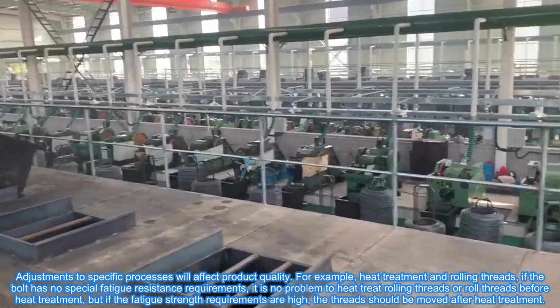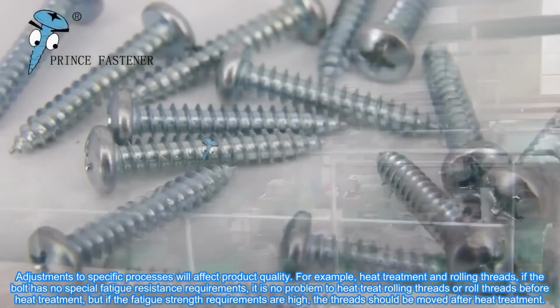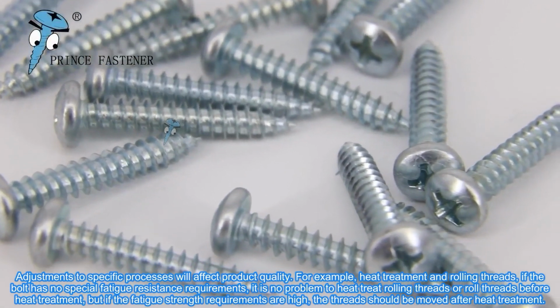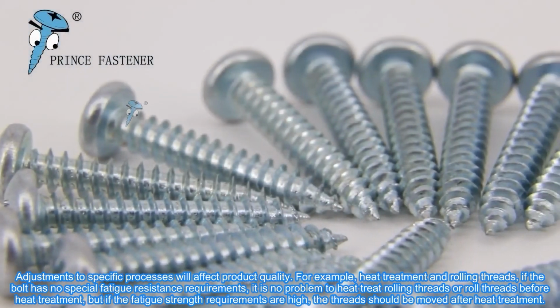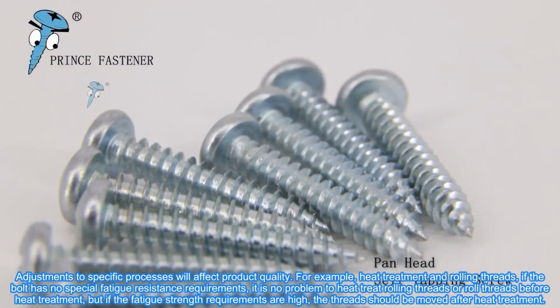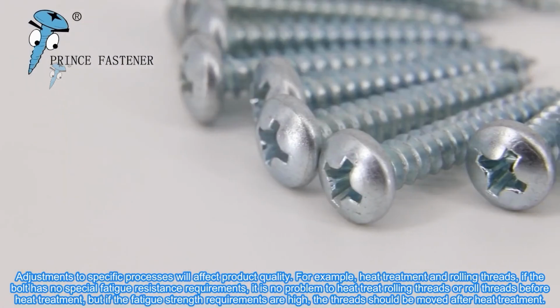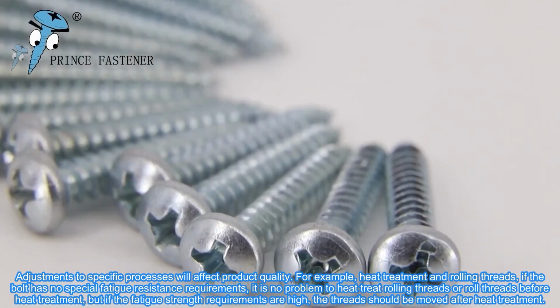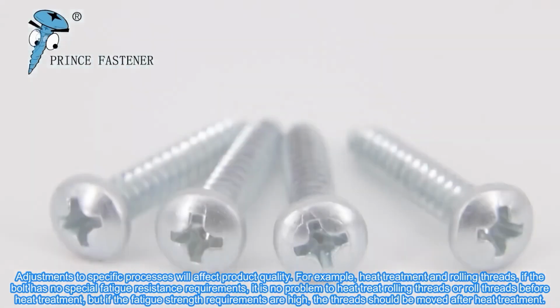For example, heat treatment and rolling threads. If the bolt has no special fatigue resistance requirements, it is no problem to heat treat after rolling threads, or to roll threads before heat treatment. But if the fatigue strength requirements are high, the threads should be rolled after heat treatment.